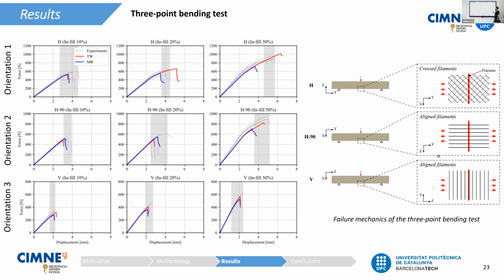And the reason behind this phenomenon is the failure mechanism that is occurring. For instance, in the vertically printed specimens, which corresponds to the 3rd row, we can see that the failure occurs always at the bottom face, and in this example, the filaments are printed in this direction, and the failure occurs due to the decohesion between adjacent filaments. In the H90 case, if we perform the same analysis, the failure occurs due to the breaking of the filaments. While in the first case, the failure occurs due to a plus minus 45 breaking of the filaments, which is a much more complex failure mechanism that is slightly more difficult to capture with this modelization.